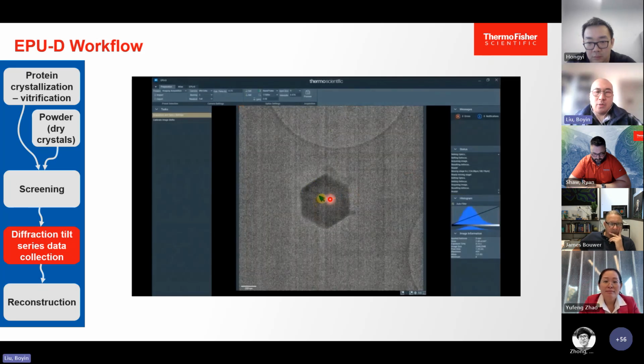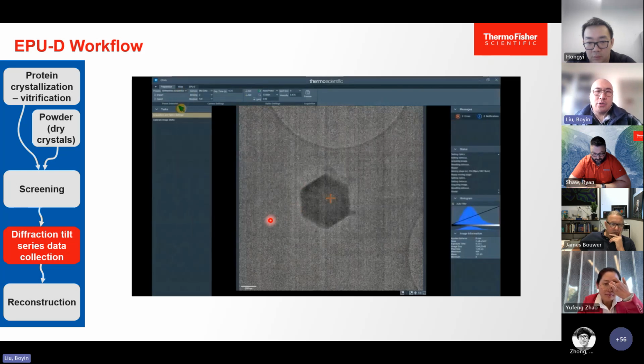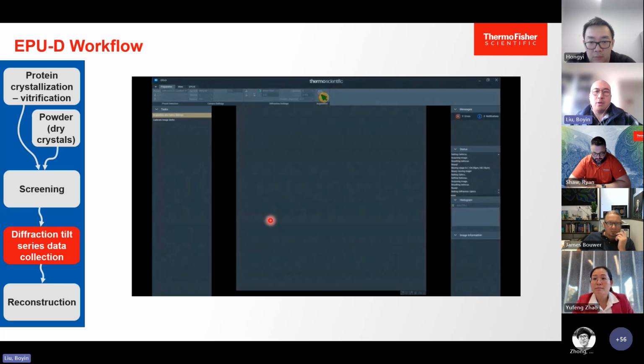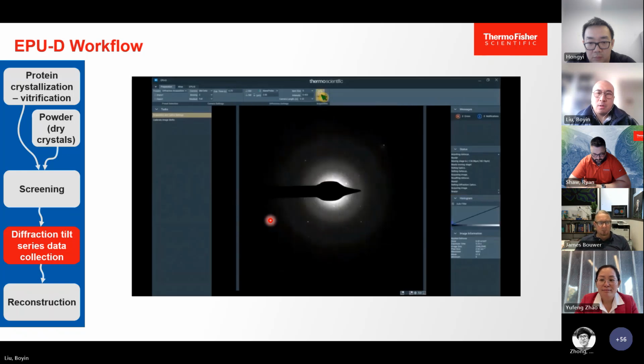This is to center the crystal again, and then go to diffraction acquisition. And then EPU actually, once you switch to diffraction pattern, EPU will insert the beam stop, switch to diffraction mode automatically, and leave the screen automatically, so you don't have to do anything. It's very easy to use. Set up the exposure time, press acquire preview, and then you get the diffraction pattern for screening purpose. Okay. So this is a bad one.